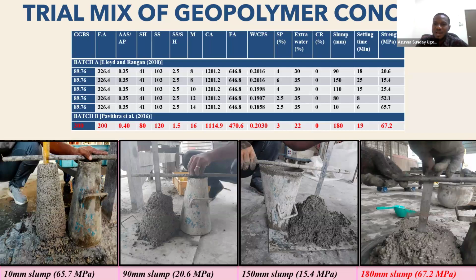Then at this point, I tried to increase the strength of the concrete. When I increased the strength to 65 MPa in the fifth mix, you see that the slump dropped to 10. So for the density method, it is either your workability is too high and your strength is very small, or your strength is very high and your workability is very small.